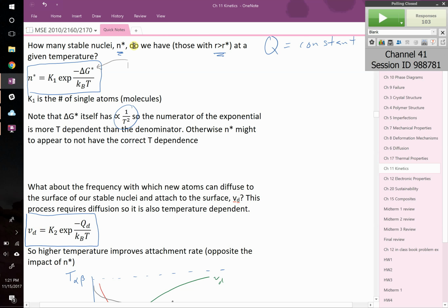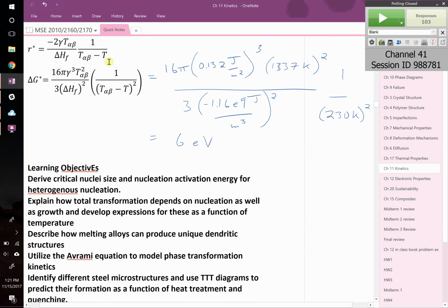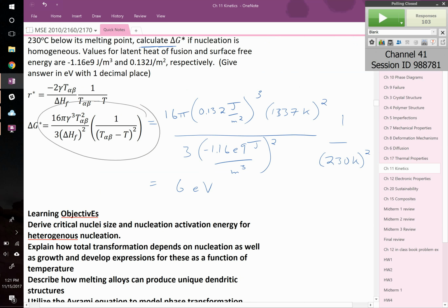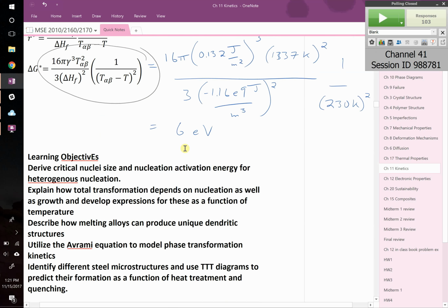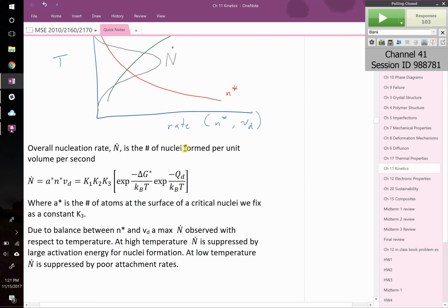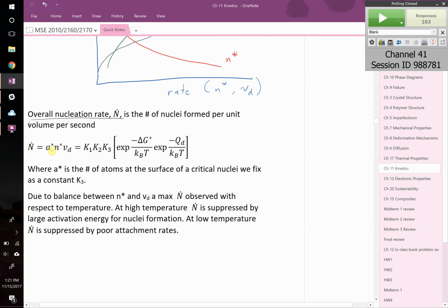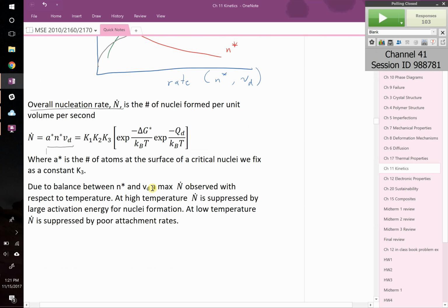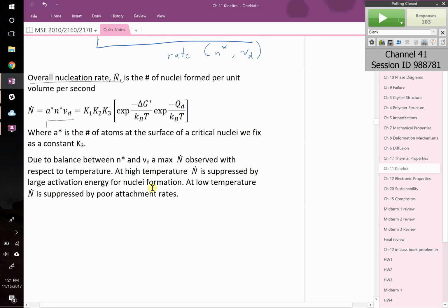So again, if you want to see the math, you can just plug all of this into that, and you'd see that it actually has a different dependence. So again, the overall nucleation rate, N dot, that's the number of nuclei formed per volume per second. That is going to be A star, N star, V sub D. A star is the number of atoms on the surface. N star we've already talked about. V sub D we've already talked about. So again, that's going to be related to our transformation rate.